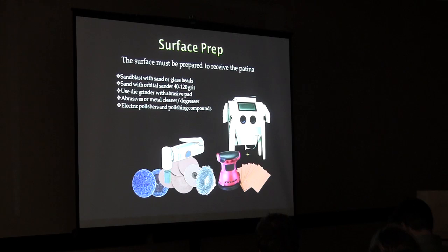When you're doing a patina, what you're looking for is enough indentations in the metal so that the patina is going to bite, sort of like pixels on a TV. The more you have, the smoother and nicer the patina is going to be. The best for anything, as far as I'm concerned, is sandblasting. If you're doing something opaque, 40 grit sand works great, alumina or silica, either one. If you're going to do a hot patina, you probably want aluminum oxide, probably 120 grit.